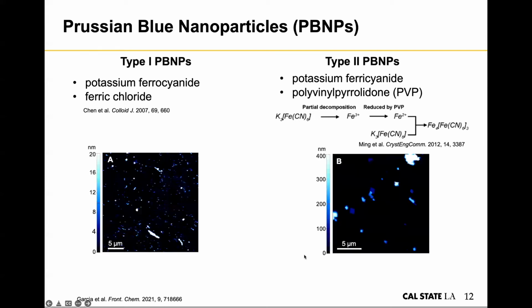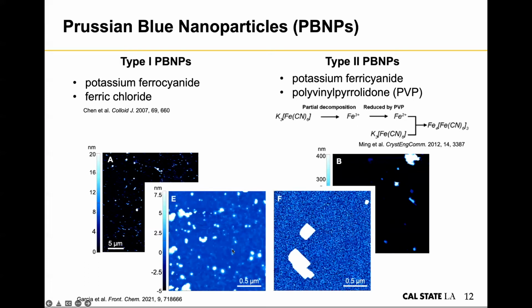And then we used AFM to characterize the product we synthesized with either method. It further confirmed that type 1 has a more random, spherical shape, while type 2 has more cubic structures with sharper edges. So then we applied these two different types of particles to see whether we can get different types of signals because their structures are different.